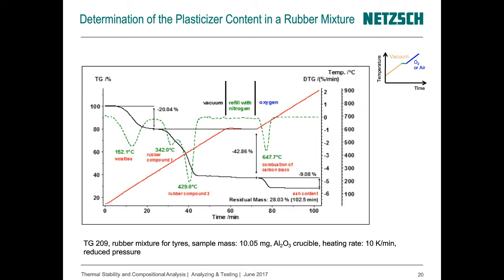A possibility to make the situation a little bit better is to use reduced pressure inside of the thermobalance, and this is given here in this graphic. So that means the reduced pressure, or how we called it here, vacuum, leads to a boiling point depression of the plasticizer, and therefore, as a consequence, the plasticizer content can be well separated from the decomposition of the polymer.